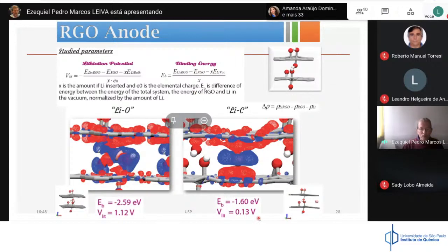On the other side, you can calculate the lithium potential, where you also have to calculate the energy of the lithium system and subtract the energy of the reduced graphite. And if you subtract the energy of the bulk, you get the insertion potential of lithium in this material referred to lithium bulk. This is, for example, the energy value you have to pay to insert lithium close to an oxidized species in this reduced graphite oxide.